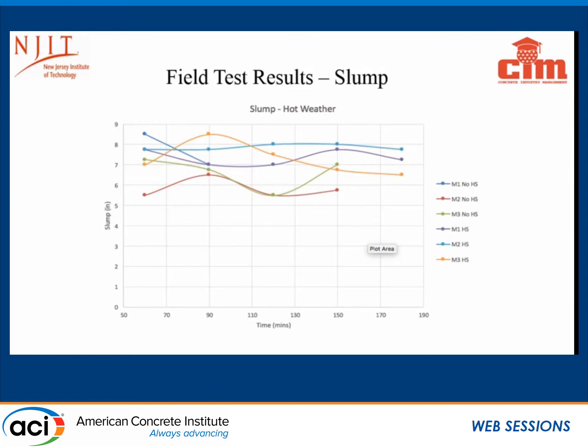As you can see here, the slump during the hot weather was fairly consistent, especially when you take into consideration the use of the hydration stabilizers, which is these mixes with hydration stabilizer. You see, it's fairly consistent right here. So that is proof that utilizing hydration stabilizers gives you a fairly consistent slump, better slump retention.